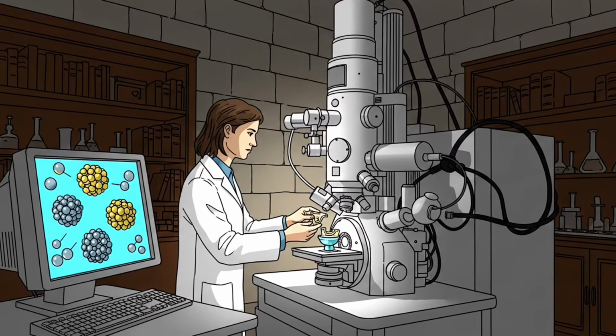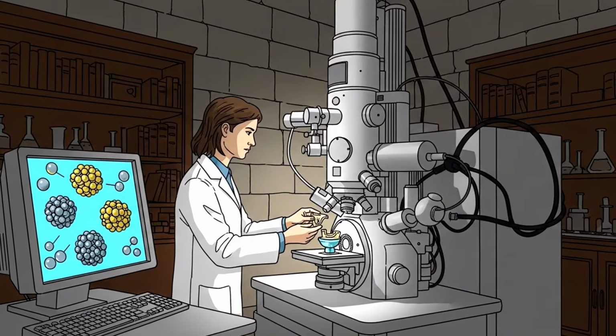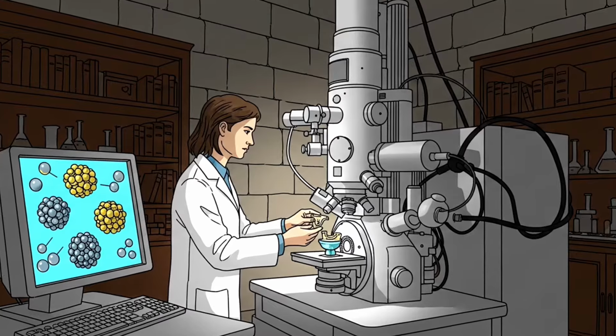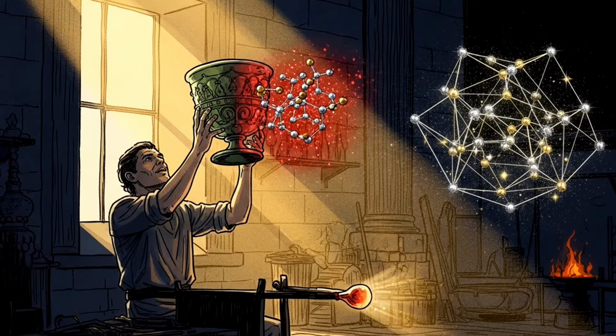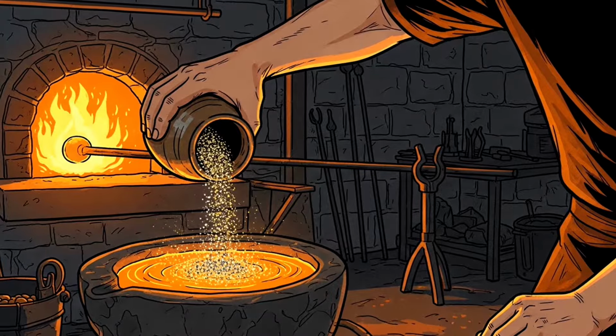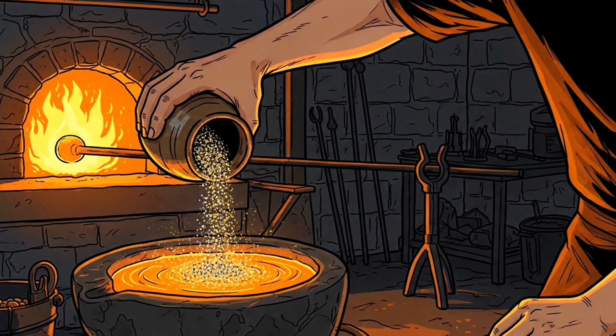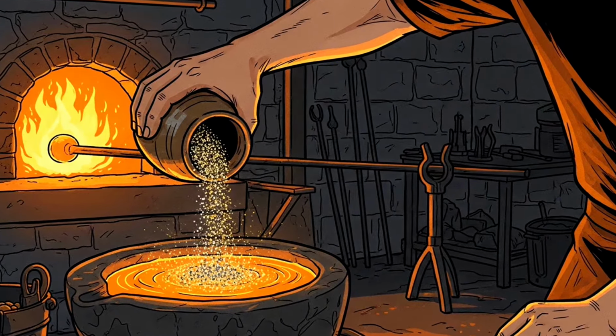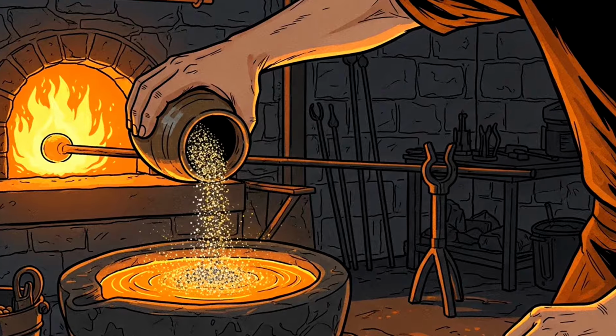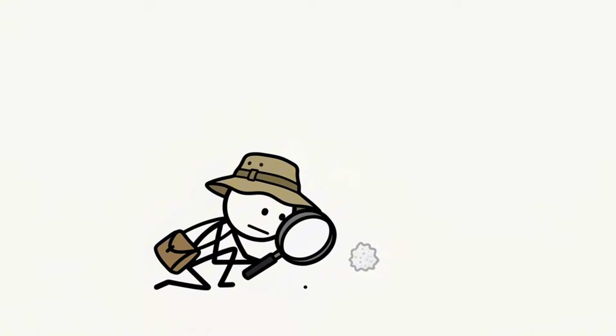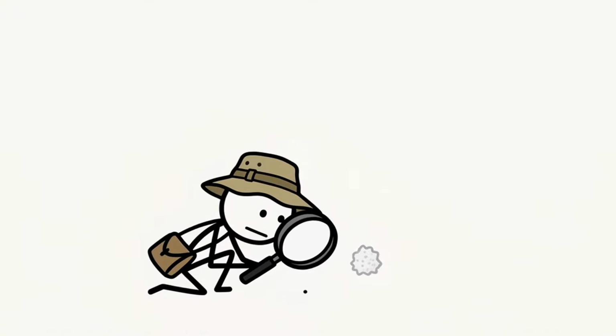Then, in 1990, researchers at the British Museum placed a fragment under a transmission electron microscope. What they found was extraordinary. The glass was infused with nanoparticles of silver and gold, ground down to approximately 70 nanometers in diameter. That is roughly 1,000th the width of a grain of salt.